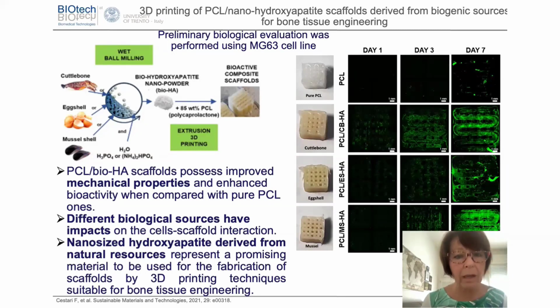So we produce some scaffolds with bioprinting by using bioceramics obtained from 3 different sources and compare with the commercial hydroxyapatite. As you can see, in this specific case, the bioceramic was combined with the synthetic polymer polycaprolactone and of course compared with the pure polycaprolactone. As you can see, also in this case the possibility to use the printer, so we can bioprint three-dimensional structures, and then we culture cells.